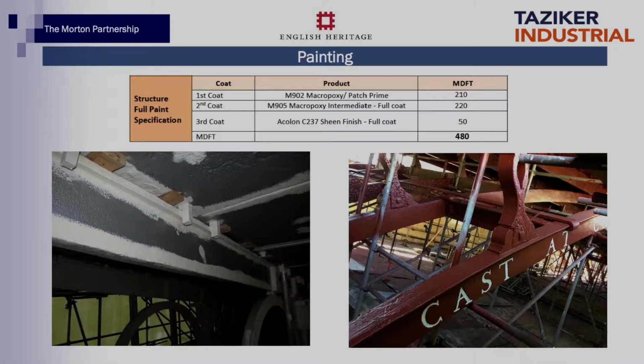It was a 3-coat paint system, 2 coats of an epoxy and an acrylic urethane top coat for gloss retention. You can see each of those were governed by an additional stripe coat. For the eagle-eyed among you, the picture there on the right, that is not an intermediate coat, that is the finished article, which has somewhat changed from the battleship grey that everybody has known the bridge to be over the centuries. The reason that it was changed to a red oxide is twofold. Predominantly, some of the original images of the bridge obviously showed it in a red, and when we went back with the archaeologists to pick away at the various layers over the years, we actually found that we believe the original colour of the structure was a red oxide.